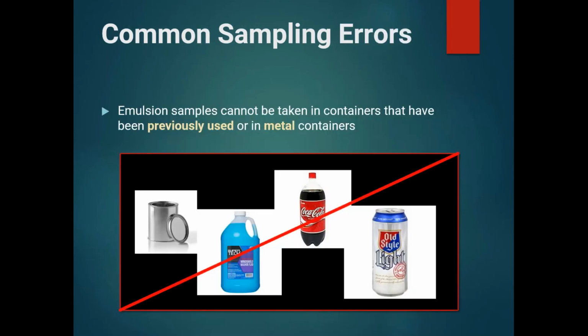Emulsion samples cannot and should not, well, they can, but they should not be taken in containers that have been previously used or in metal containers. The metal itself can interact with certain types of emulsions and cause some instability of the emulsion in the container itself. These are some examples of containers that do get used in the field and that we do see in the lab. Again, all of these are just a source of contamination. You can contaminate your emulsion before it ever gets to the lab to test.